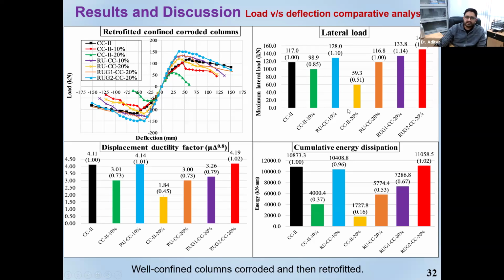Okay. Then for a column which was corroded to 20%, the reduction in the lateral load capacity was 49%. So we only got 59.3 kilonewton, whereas it was 117 kilonewton over here. So you can see 49% reduction. Then we retrofitted it with UHPFRC only. You can see RU over here. Then we retrofitted it using RU G1, that is 1 layer of GFRP, and 2 layers of GFRP. So just by having RU, that means only retrofitting with UHPFRC, we recovered almost the same strength as it was in the control column.